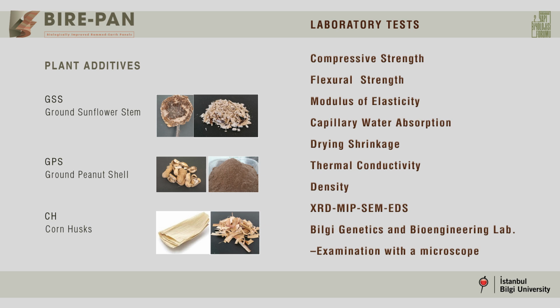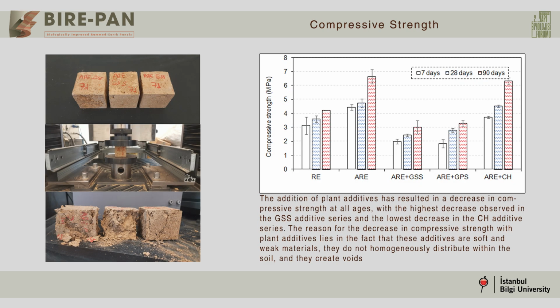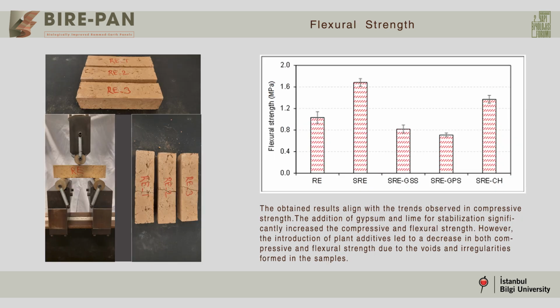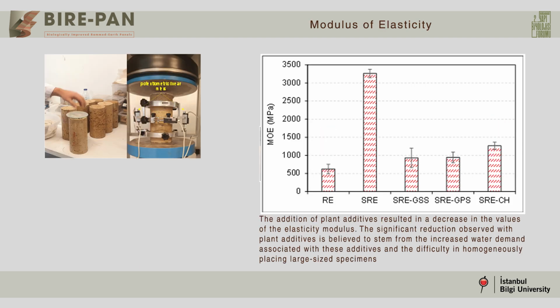We can see the decrease in compressive strength at all ages, with the highest decrease observed in the GSS additive and the lowest decrease in corn husks. The obtained result aligned with the trends observed in compressive strengths. Also, you can see the highest decrease in GPS and lowest decrease in corn husks. Modulus of elasticity: a significant reduction was observed with plant additive. The highest performance is the SRE recipe.